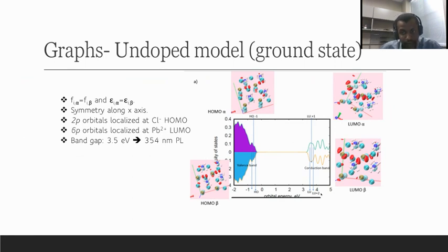And at the HOMO and LUMO, we also looked at the partial charge densities to look at the orbitals. At HOMO they are localized at the chlorine, and they look like p orbitals. And then at LUMO they're localized at the lead, and they are p orbitals as well, but different p orbitals than the ones at the chlorine. Next slide, please.